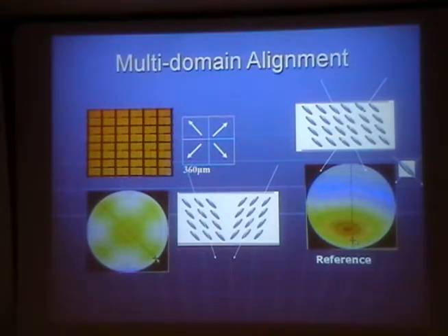Liquid crystal displays were notorious for incredibly poor viewing angle characteristics because of the optical uniaxial anisotropy. Depending on the angle you're looking at the display, the visibility can be good, extremely bad, or completely reversed.